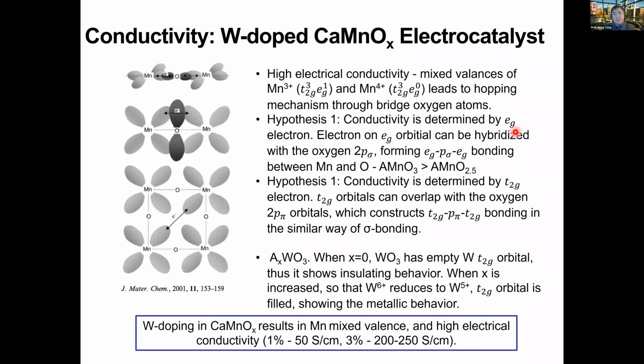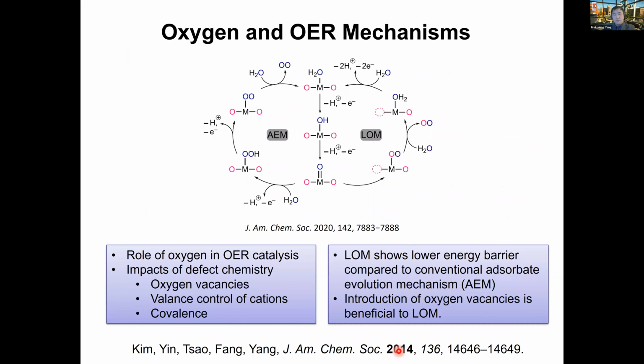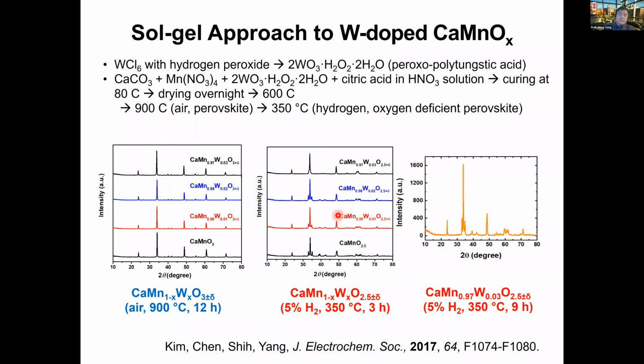The conductivity could be determined by eg orbital electrons, for instance, through these interactions. Also, it could be conductivity determined by t2g orbitals through the bottom type of illustrations. And that's all related to the overlap between oxygen and the metal bonds. So by having tungsten doped in the system, the conductivity can actually change. This is a summary of what we can do. If you have 1% to 3%, these are the reported values. What we figured out is that, in this particular system, if you try to maintain a phase pure system, we can dope tungsten to about 3%.